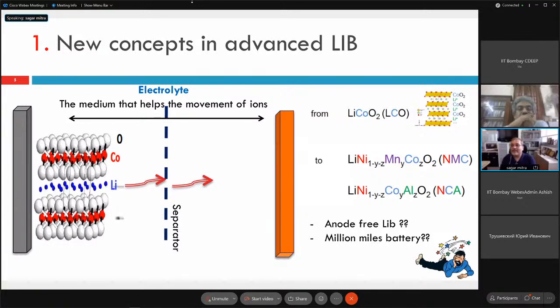And once that happens, after charging, this battery is complete now. Now lithium acts as a lithium metal anode, and the other side is LCO. And again, on discharge, this lithium will go out and then go to the cathode structure. This is well known. So what benefit am I getting if there is no graphite? I am getting the weight advantage. I am not using that graphite weight, so I am increasing the energy density.